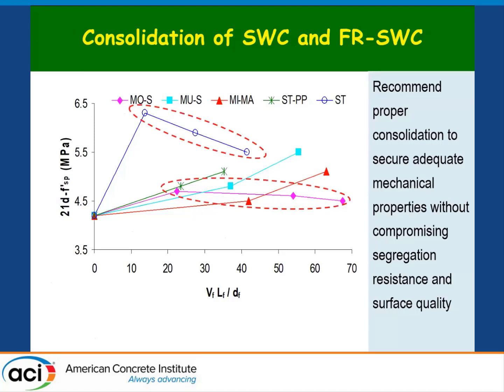So these are some typical characteristics. First one here is the fiber reinforced super workable concrete versus fiber reinforced SCC. The slump flow obviously is lower than the SCC. The diameter over the height is below 12 versus above 12, all the way to 23. The blocking ratio is 0.2 to 0.6 versus 0.6 to 1. And the surface settlement, we also showed that is really not effective.